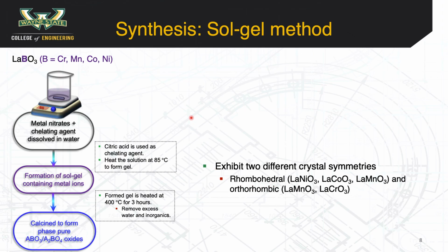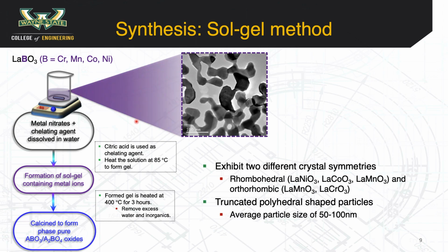In order to synthesize these oxides, a sol-gel based method is used, where stoichiometric amounts of the A site salt, which is basically lanthanum in this case, and the B site salts are dissolved in water. Citric acid is then added as the chelating agent to bring the metal ions together. The resulting solution is heated at 85 degrees Celsius, resulting in the evaporation of water and the formation of a gel. The formed gel is then burned and calcined at temperatures of interest to form the oxides of interest.